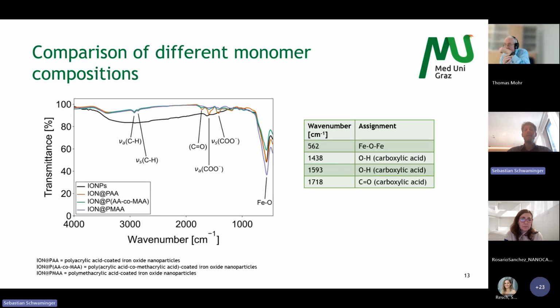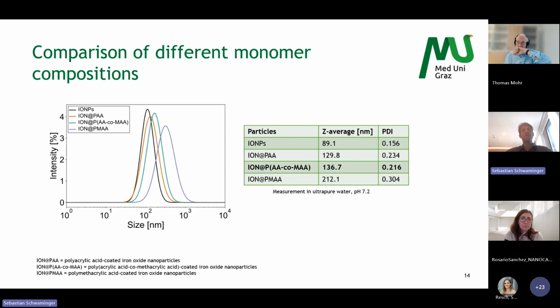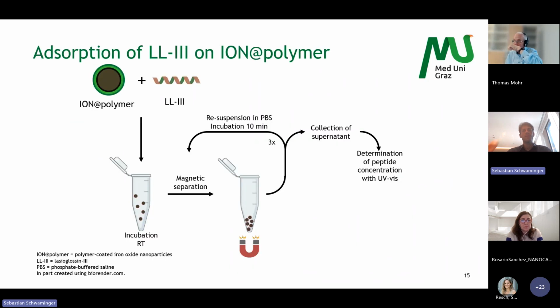Then we analyzed, figuring out if the polymer really works and is still bound to the iron oxide particles, with different techniques. We characterized the particles with IR spectroscopy as well as with dynamic light scattering, being able to show that these nanomaterials are still in the nanoscale range. In our case, it's usually below 200 nanometers. There was one exception, but usually it's between 100 and 200 nanometers.